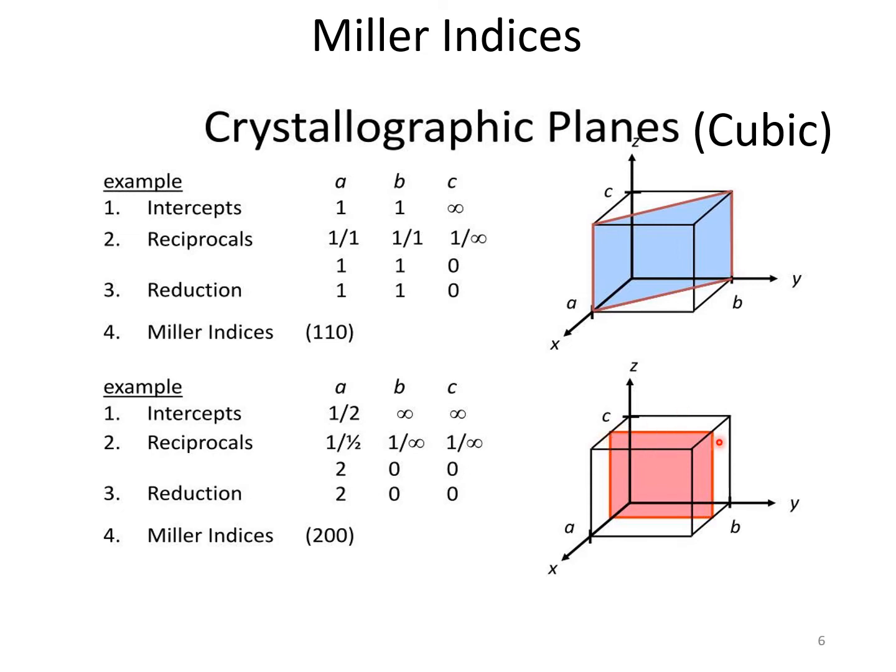300 would be planes that are spaced at 1/3 of the spacing along the x-axis, a spacing of A upon 3 along the x-axis. And that's how you would basically assign, know what planes you're looking at.